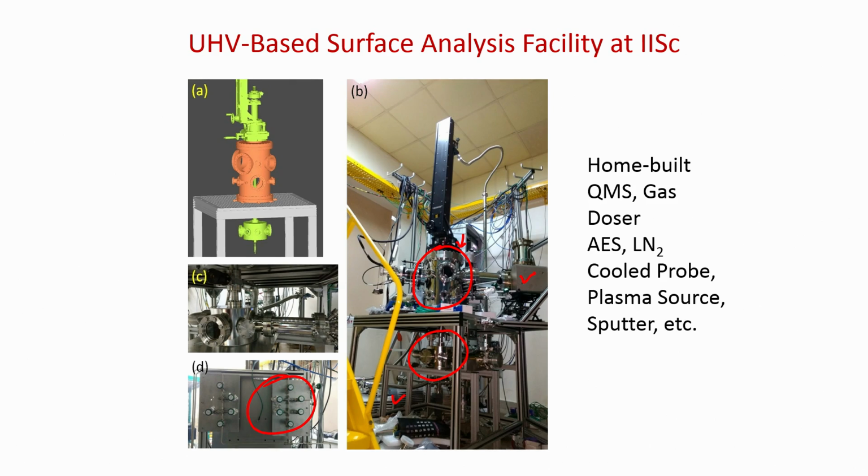This is a little complicated chamber and analysis procedure, but the primary idea of building this whole chamber is to create the vacuum first and maintain that vacuum at the level of 10 to the minus 10 torr, so that one can perform the experiment before the surface is contaminated. At room temperature, contamination will be very quick, within a few microseconds.